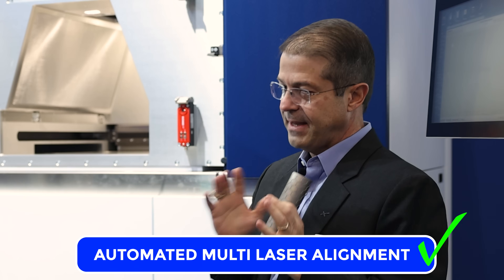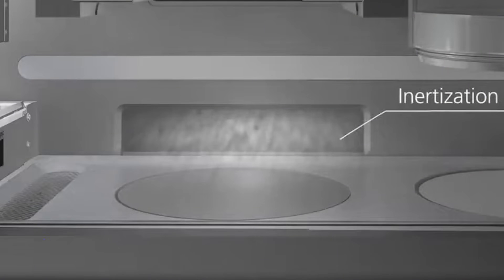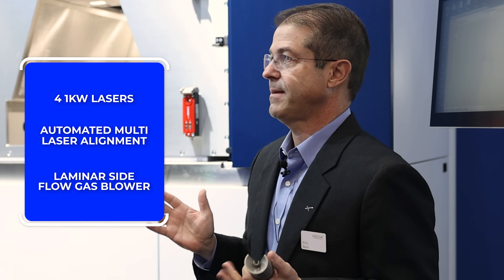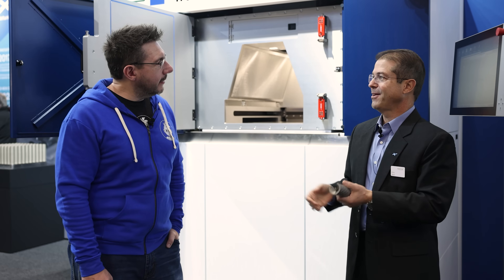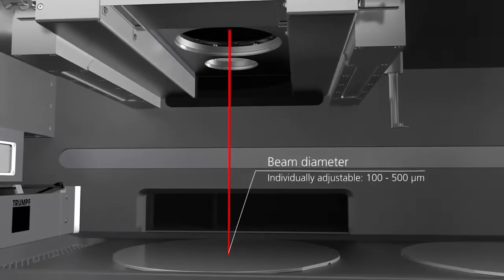Automated multi-laser alignment — that's key. The next most important thing in a laser powder bed fusion system is the gas flow, because we're running inert gas across the build surface to take away the smoke load that comes from the melting process. Lasers have to get to the surface, and they can't go through the smoke and spatter, so you have to clear that away. We use a laminar side flow technique, as opposed to a top-down technique, and we were able to show that the gas flow dynamics are everywhere the same on the build plate. That's key, because if you're building a part in the outer corners versus the center, you need the same laser intensity and the same gas flow dynamics, because those are the two physical properties that define the material characteristics of the part.